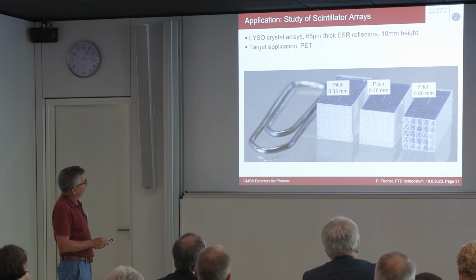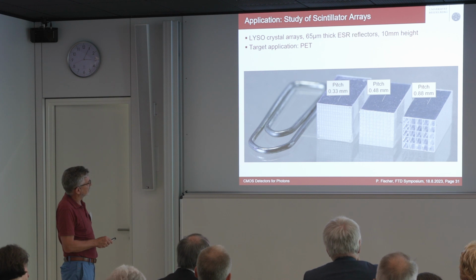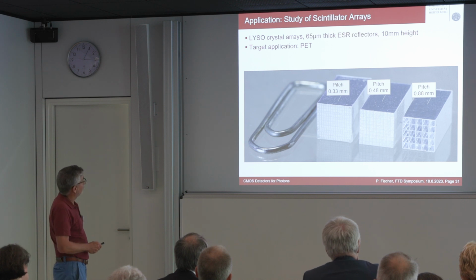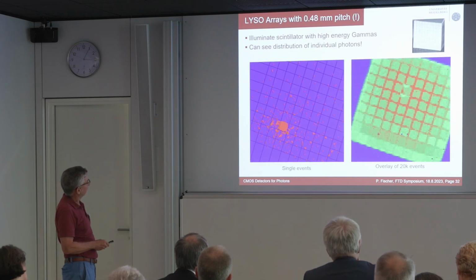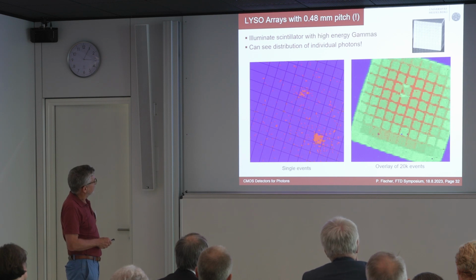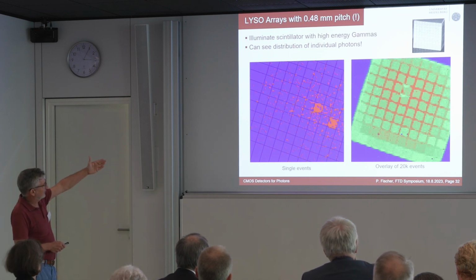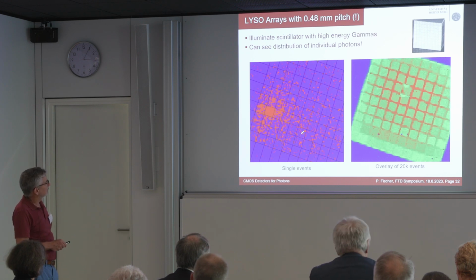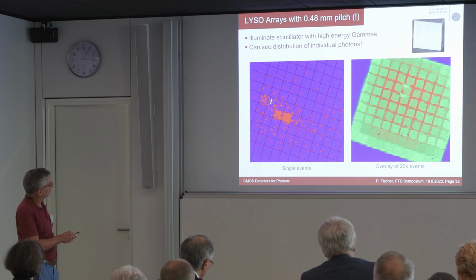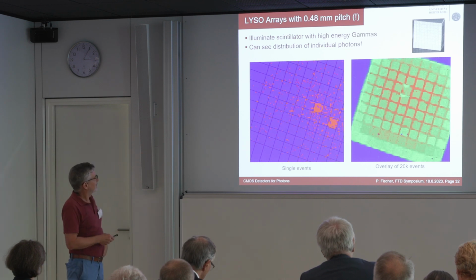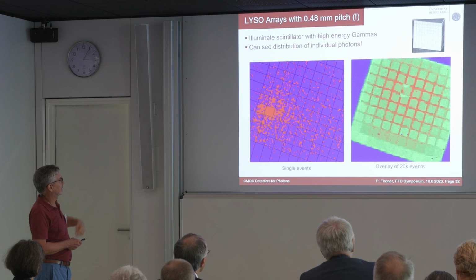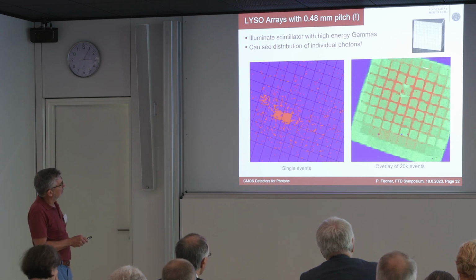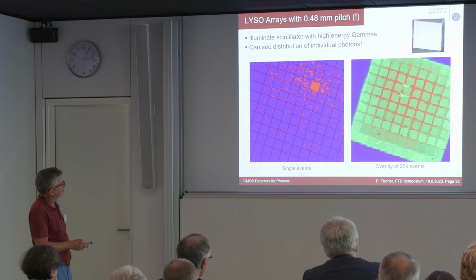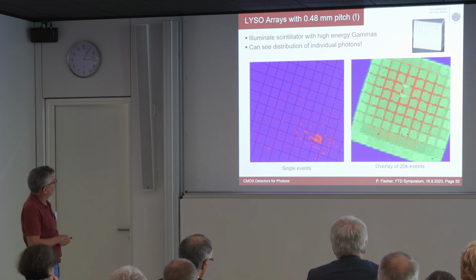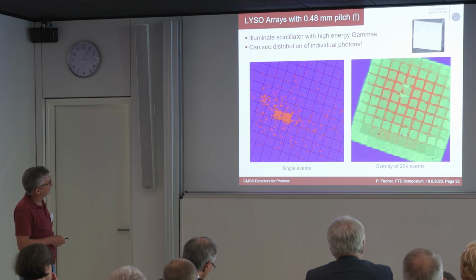So we have bought some of these scintillators, and look at this one. These are long needles of this crystal in 0.5 millimeter pitch. And if I now put this on our detector, we take single events. So these are single events where we see photons coming out. And every red cross is a spot which has fired for one particular event. And if you superimpose all these events, you can see the grid structure. You can draw these lines, and you can really see how the events look.